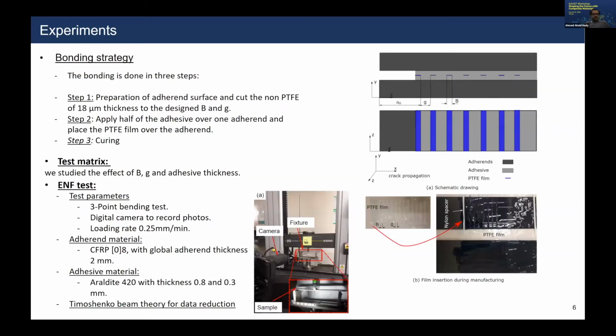I will touch just on the manufacturing process and the test, because the bonding strategy is a bit different from the normal bonding strategy. First we apply half of the adhesive on one of the adherends, then we place the PTFE film, which is marked in blue here. Then we put the second half of the adhesive, and then we cover with the second adherend. So the structure of the joint is something like this, with the gap G between two successive cracks and crack width B. In the test matrix in this study, we study the effect of B, which is the crack width, and G, the gap between two successive cracks, and the adhesive thickness.